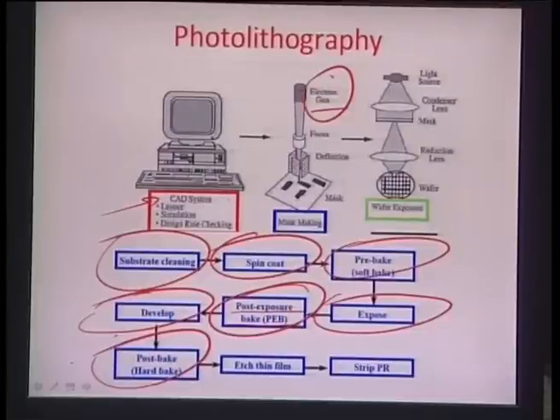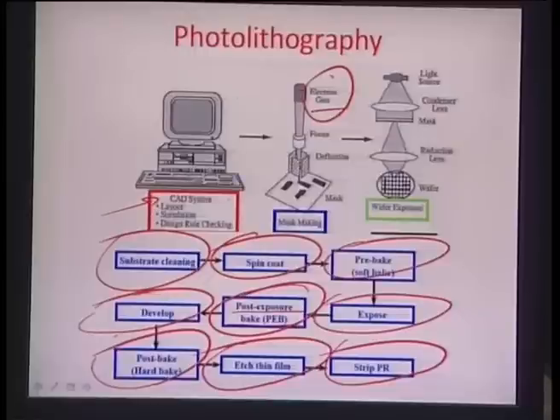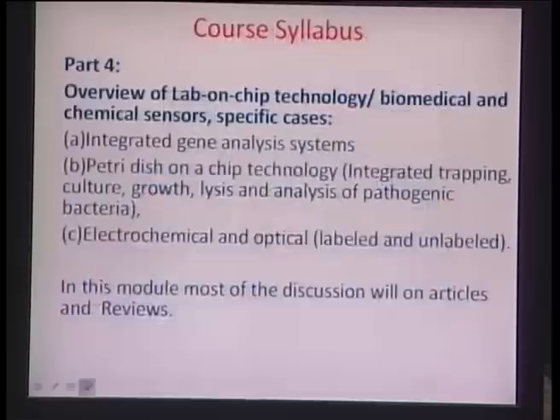You then can do, of course, a lot of different things, like if you want to use this resist as a sacrificial mask, you can use this to etch off the material by creating a layer and opening these vias at different places through which you can give this etchant and can etch relatively thin films of silicon dioxide, nitride, some other materials, etc. And then of course you can strip the sacrificial photoresist, because dissolving in an organic solvent like acetone would essentially eat away the resist which is left over on the surface. So this entirely is a process of photolithography, and we will be looking into a lot more details and other aspects of this process as we go along in the microfabrication.